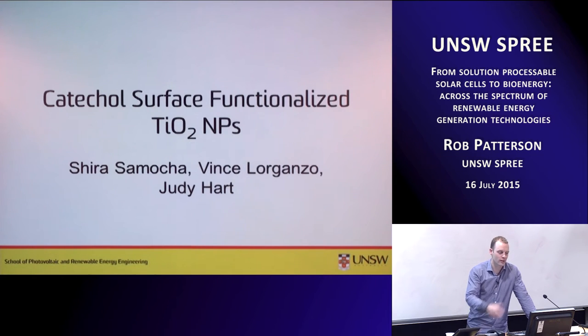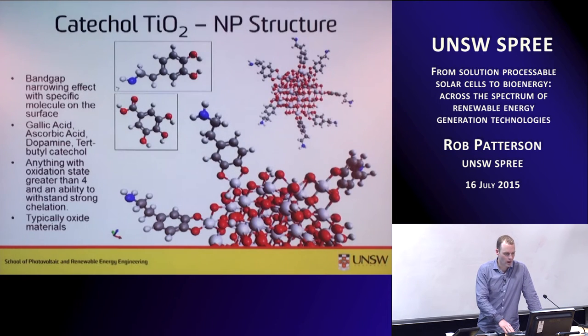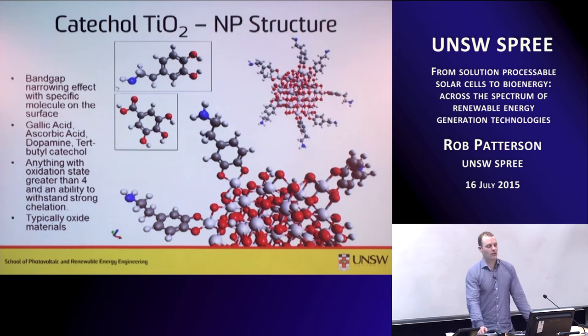Catechol surface functionalized TiO2 nanoparticles is the next thing I want to talk about. And this is done with people in materials science. And here's a picture of the structure. This red and white blob in the middle here is a TiO2 nanoparticle. The way this material is formed is we use a very strongly chelating molecule to attach to the surface. And chelating means that it's aggressive. It goes in on the surface and attacks it very strongly.